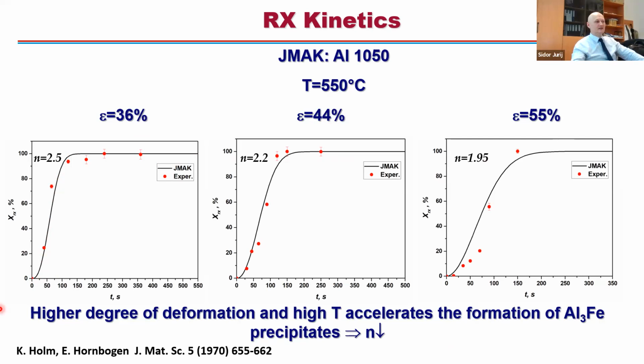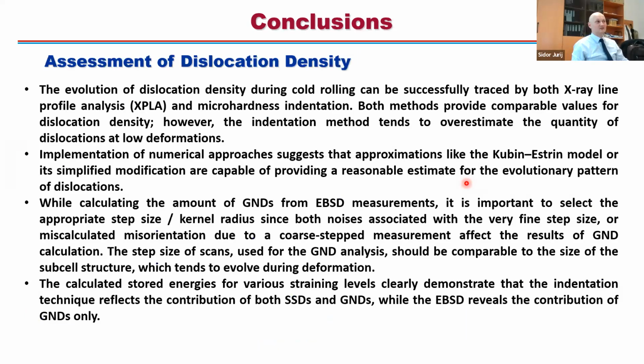And then we analyzed again earlier papers from the 70s, the work of Holm and Hornbogen. What they claim is that in fact a higher degree of deformation and high temperature accelerate the formation of aluminum-iron particles in similar systems. They did a lot of TEM work, and therefore n tends to drop. In fact, when you have higher straining levels, the formation of precipitation is more likely, and these precipitates will slow down the recrystallization, and therefore n tends to drop. So you have to take into account all these microstructural features.